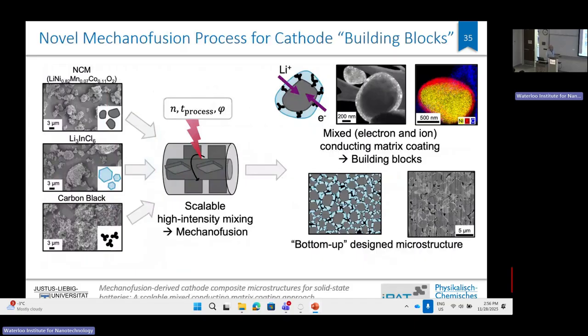As part of that cooperation, they came up with a nice idea of a kind of chemical mechanofusion process for cathode building blocks. So what they do is mix cathode material in a dry process with a solid electrolyte, which is a halide electrolyte, and they create a little shell of electrolyte with a bit of carbon that is able to deliver electrons, as a kind of shell around the cathode particle. And these are then a powder that is a building block for nice cathodes that operate quite well. So this is fully scalable. This is a mixing process. We would not have done that without cooperation with engineers on particles.